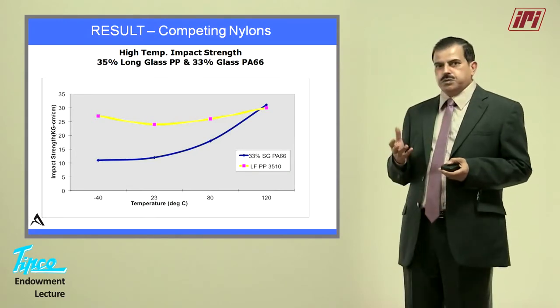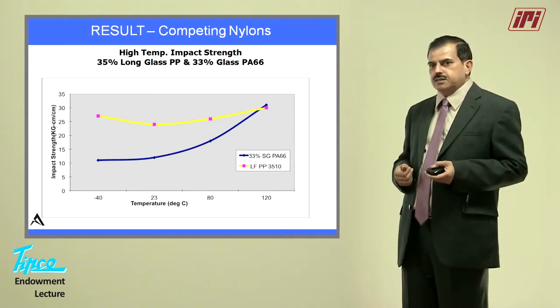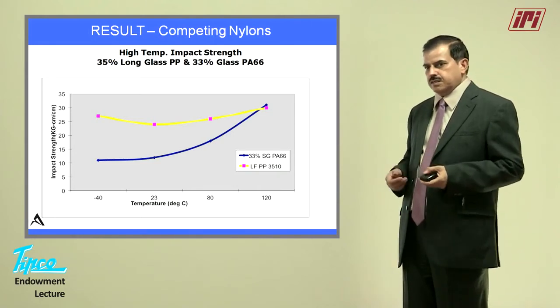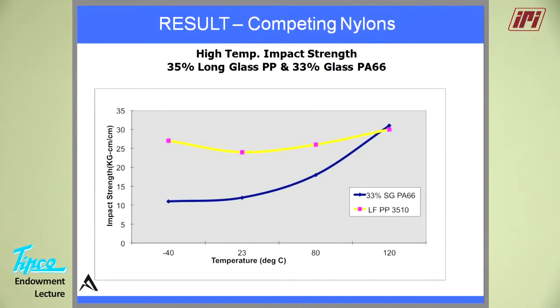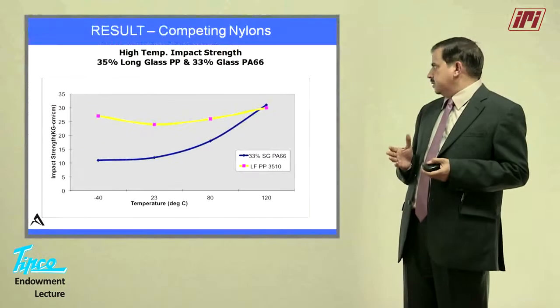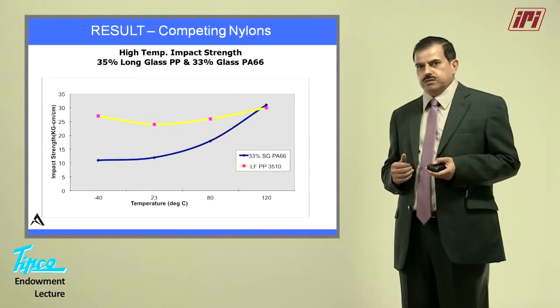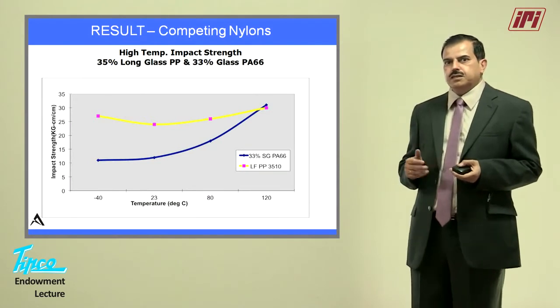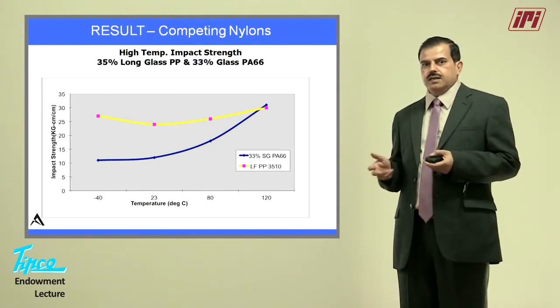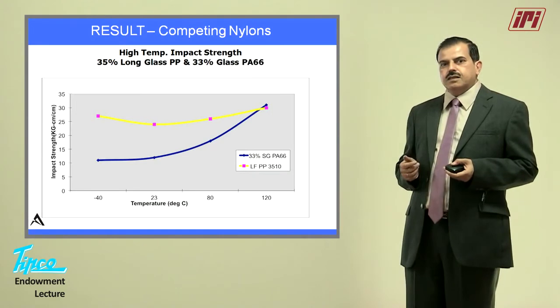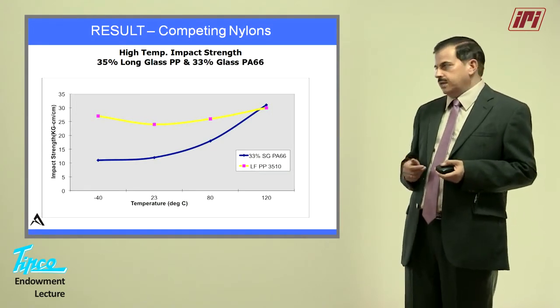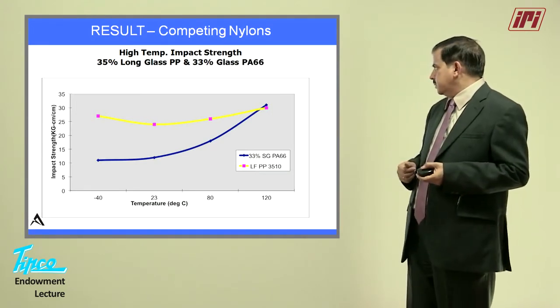Impact strength, as I told you, is quite high because of the structure it retains even after burning the polymer. That is the reason why at sub-zero temperatures, the impact strength further improves. It doesn't go down. So that is something very unusual with plastics, because at minus temperatures, generally plastic tends to become more brittle. This is opposite.